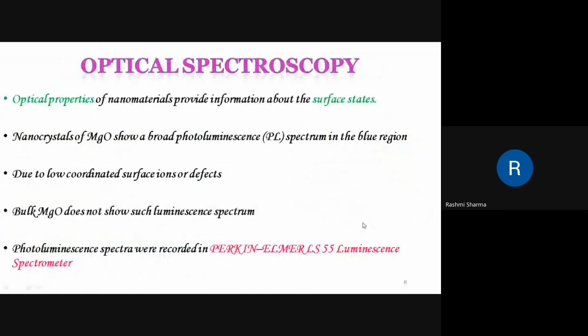So now we move on to the optical spectroscopy. Optical properties of nanomaterials provide information about the surface states. These nanocrystals of magnesium oxide show a broad photoluminescence spectrum in the blue region. It is due to the defects present at the surface, but the bulk magnesium oxide does not show such a luminescence spectrum. Photoluminescence spectra were recorded using a Perkin-Elmer LS55 luminescence spectrometer. This was the instrument used for getting the optical spectroscopy results.